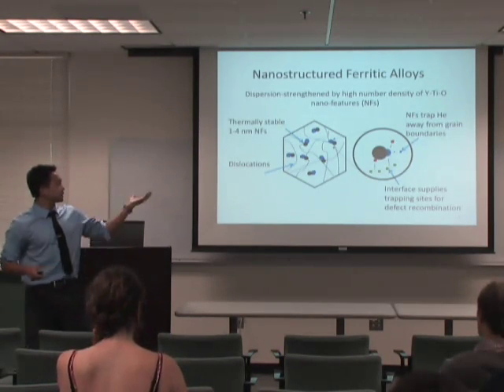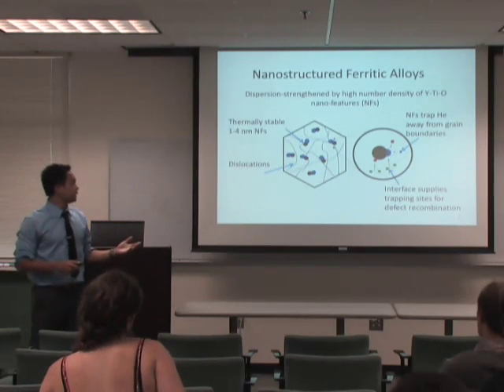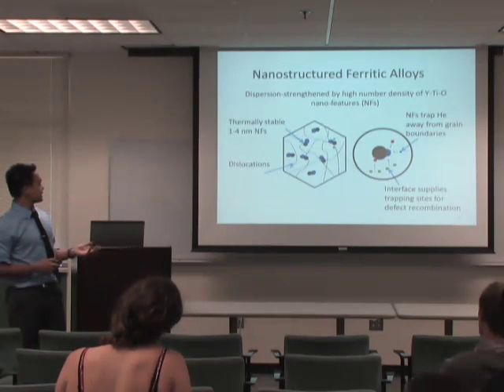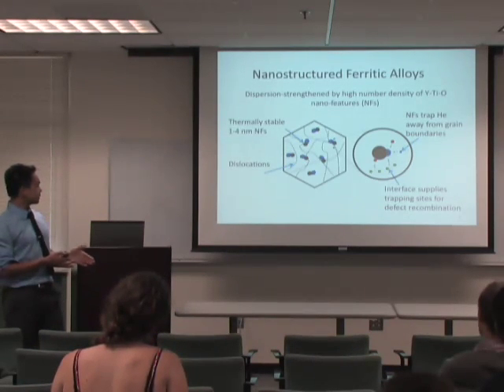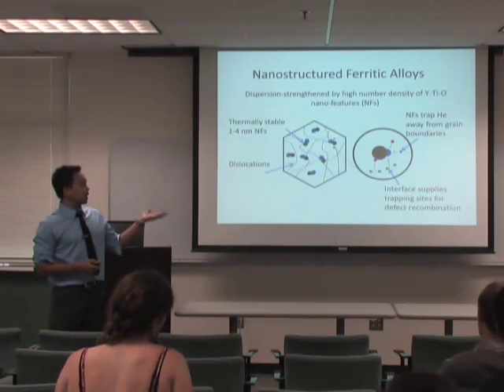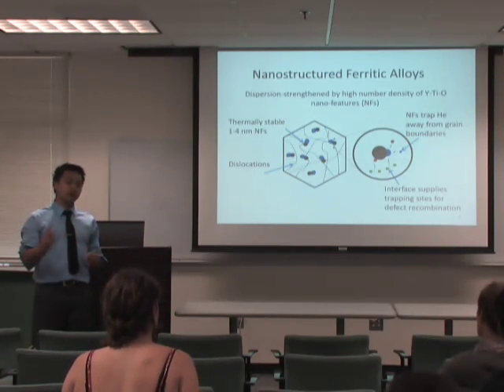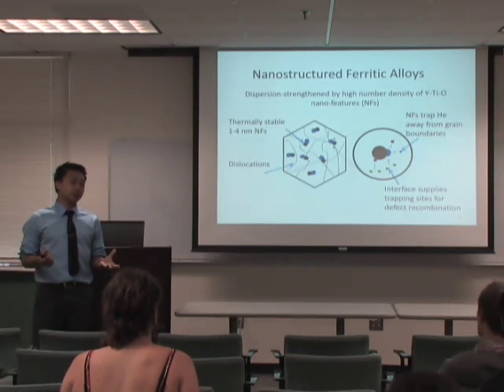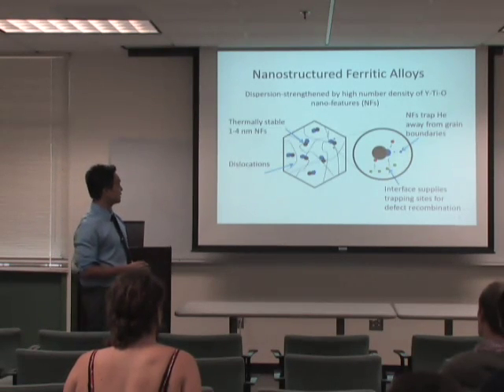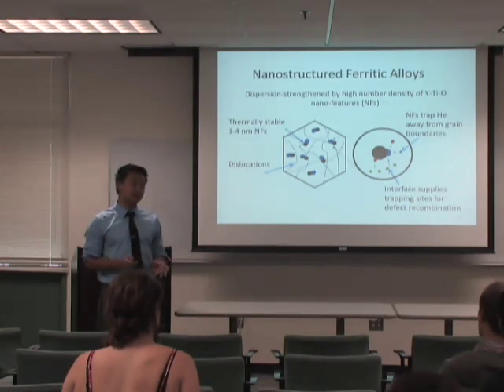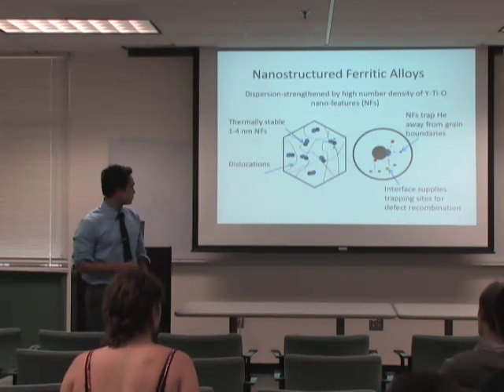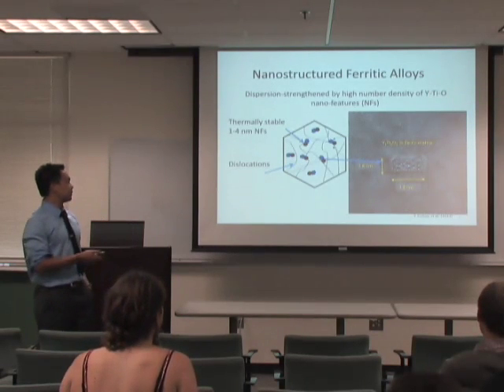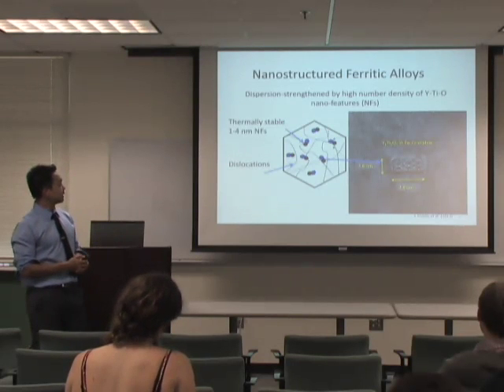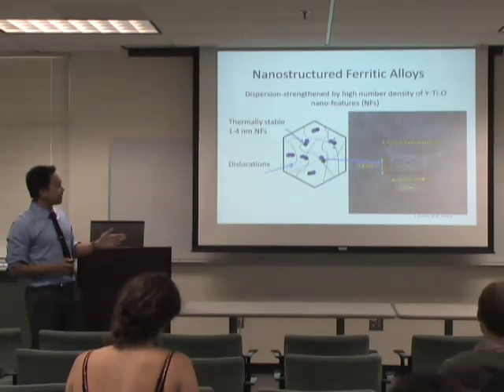for short. And these NFs are made of yttrium, titanium, and oxygen. These nanofeatures are about 1 to 4 nanometers in size. They impede dislocation in the material to strengthen the material. They trap helium and prevent them from going to the grain boundary and forming voids, which can embrittle our material. And lastly, these nanofeatures can serve as a healing mechanism from damages due to the neutron. And visually, under a TEM, we can see that this rectangle here is our nanofeature, and it's 1.8 nanometers by 1.8 nanometers by 3.8 nanometers. And they're made of yttrium, titanium, and oxygen.